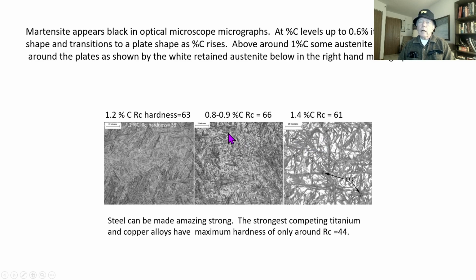So here we are at 0.8 to 0.9, and we have a mixed structure of plate and lath. Over here at 1.2, where we've increased it, it's mostly all plates. They look like fuzzy things. But when the retained austenite appears, it sharpens the boundary, and you can see them clearly.